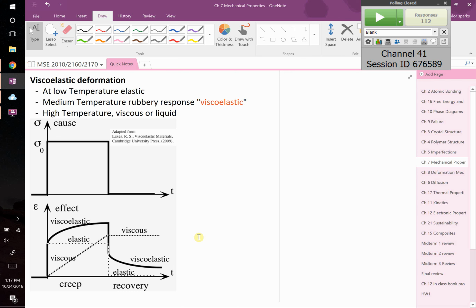So it breaks van der Waals bonds at one end, and then it reforms them at the other end? Exactly, and it forms them better because now the chains are nice and lined up. So then why, when you let go of it, if it's pretty happy where it is and very well bonded, why does it relax? It won't always. Oftentimes polymers, if you stretch them, are permanently deformed because the polymers don't want to go back at that point. I mean, there's an entropic component that says go back, and that's why rubber bands go back. But yeah, you've increased bonding. So it's going to be a balance between enthalpy, which has to do with the bonds, and entropy, which has to do with disorder. And it strikes a balance.